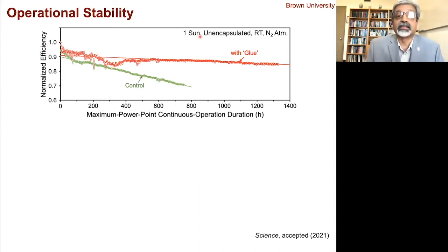This is continuous 1 sun. These are naked solar cells, not encapsulated, at room temperature. And the efficiency is degrading, whereas the one with the glue is going strong. So for example, we can calculate the life of the control is about 700 hours under this continuous illumination.